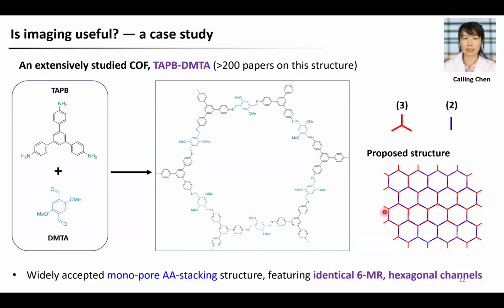Traditionally, people believe this COF has a very simple, very straightforward 2D hexagonal layered structure. Each layer consists of 6-membered pores in regular hexagonal shapes, and all the layers are identical and aligned perfectly without any misorientation, forming the so-called AA stacking mode. If you look into the literature, there are more than 200 published papers on this particular COF material, and in all these papers, this structure was taken for granted without any question.